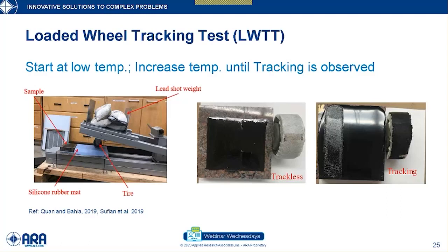Okay, so the curing of all the stone tiles that were applied with the tack coat was 1 hour, because I found out that it was properly set within 1 hour. If I'm curing the stone tile at 60 degrees Celsius, after 1 hour it reaches 60 degrees, and it doesn't matter how long you cure, it will be 60 degrees Celsius. So the bottom line is 1 hour is sufficient to achieve the test temperature you want for the LWTT test. So I use 1 hour as the minimum curing time.